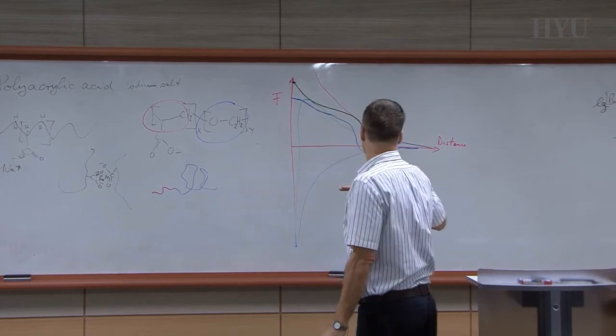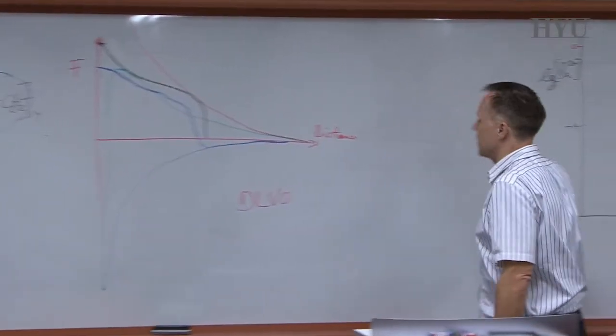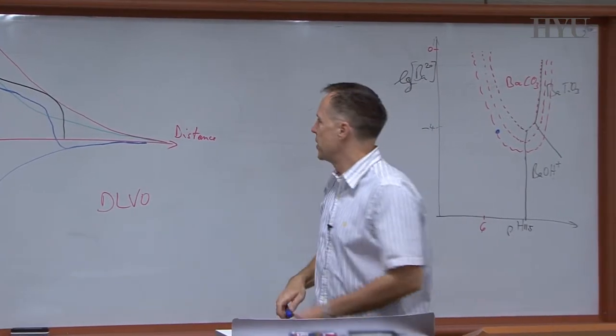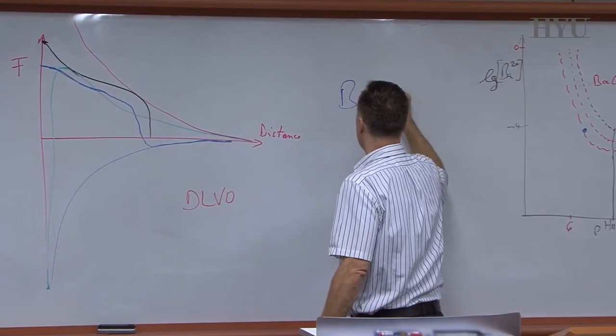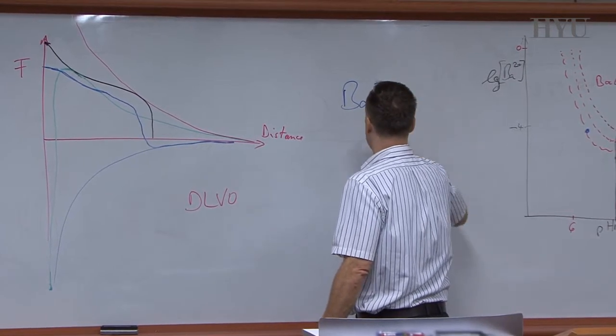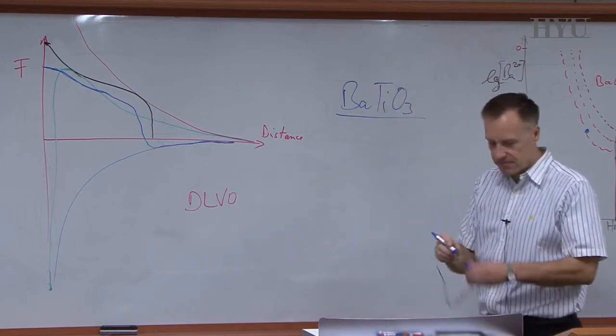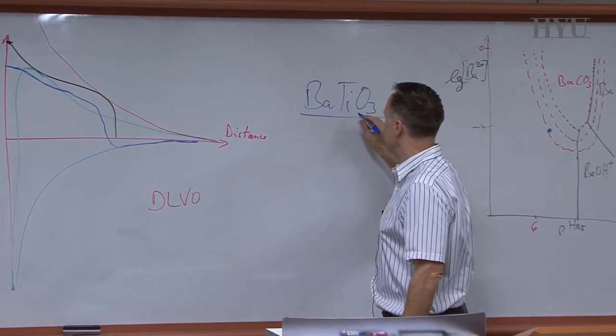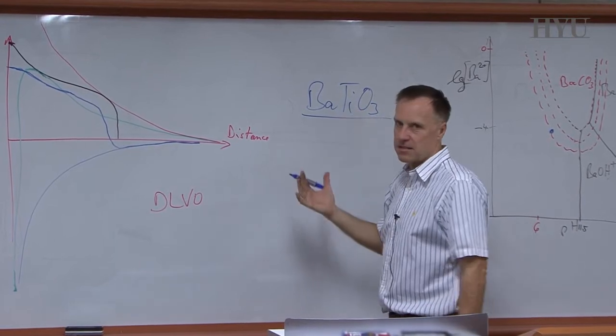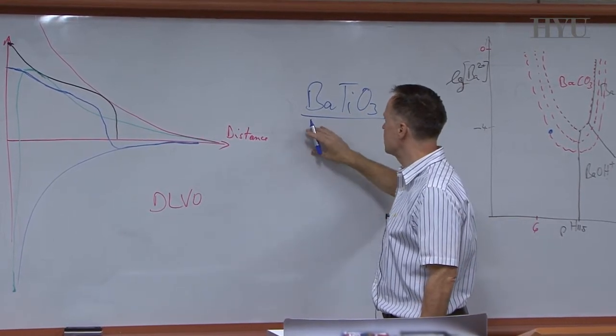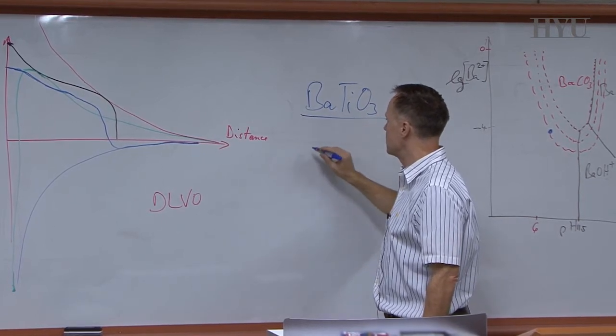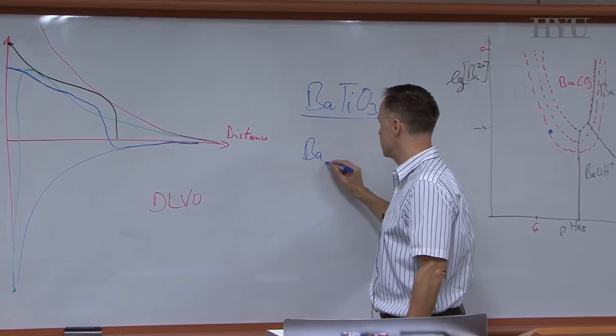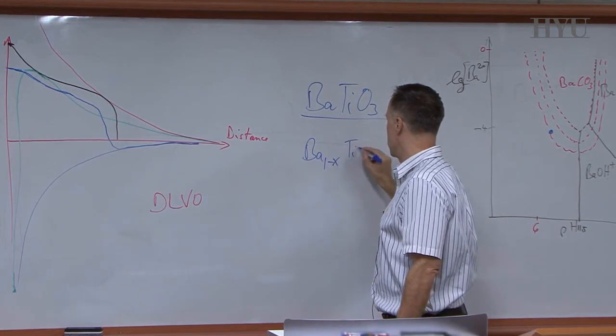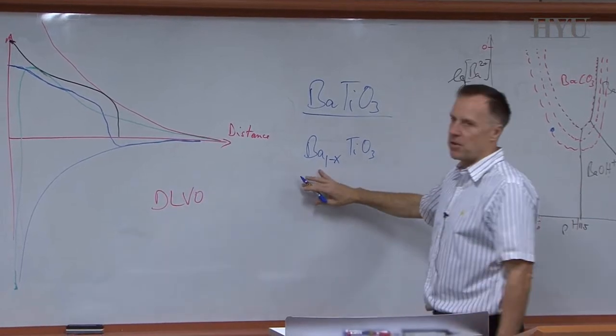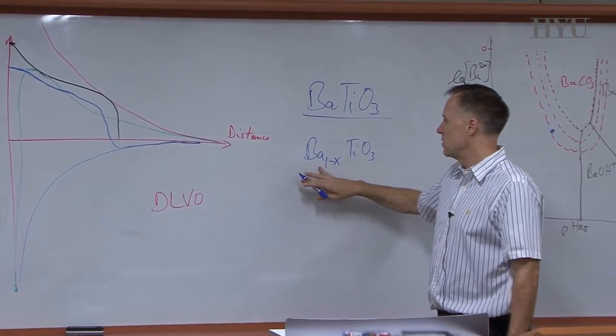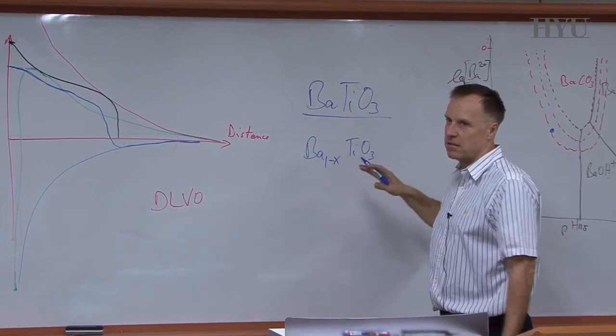So the key thing is, of course, we want to achieve barium titanate, and we want to have the barium titanate really stoichiometric. Because barium titanate, when it comes into the final steps, where you now have the particles and they have to sinter together, that these particles have then to be of a certain size. And if you sinter particles and they are not stoichiometric, let's say you are barium deficient, Ba 1 minus x TiO3, so barium deficient, then you will be rich in titania. That means